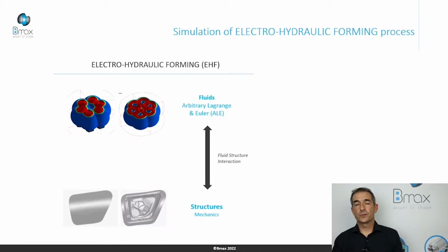That's why we use the usual dynamic mechanical solver of LS-DYNA to calculate the stress and strain in the component and in the blank, and we make a full coupling with the ALE solver, arbitrary Lagrange and Euler, to have an Eulerian approach to be able to calculate the wave propagation through the liquid, water in the case of EHF. And we directly apply a coupling of this pressure wave on the blank, thanks to a fluid structure interaction. It's like a numerical contact.